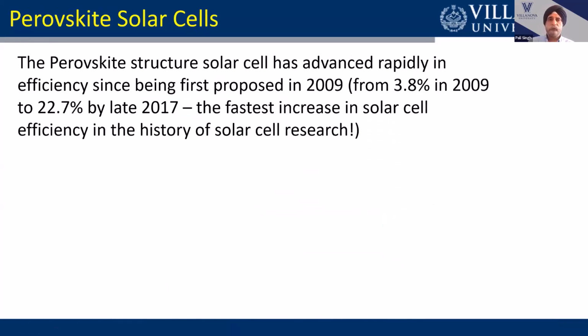So all the buzz right now is around the perovskite solar cells. And these are cells that are relatively low cost, use readily available material, and have shown an exciting growth in the advancement of the technology. So perovskite solar cell structures were first proposed in 2009, and their efficiency at the time was around 3.8%. In late 2017, the efficiency had increased to 22.7%, which is the fastest increase in solar cell efficiency in the history of solar cell research.